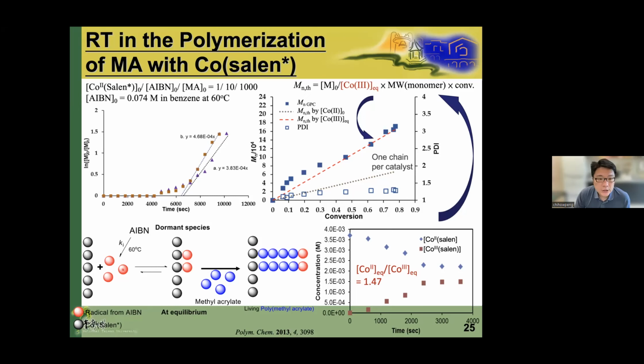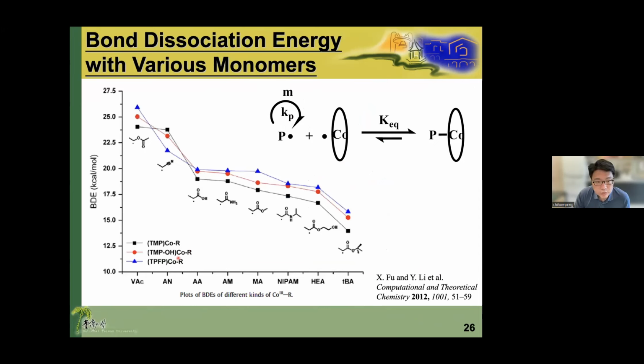That's because when the monomer transfers to the radical species, they actually have different energy. So consider the equilibrium in cobalt-mediated radical polymerization. You can see the cobalt-2 deactivates radical to form organocobalt-3. So in this equilibrium, you can understand that if the radical has a higher energy, the equilibrium will go to the right-hand side and prefer the product of organocobalt-3.